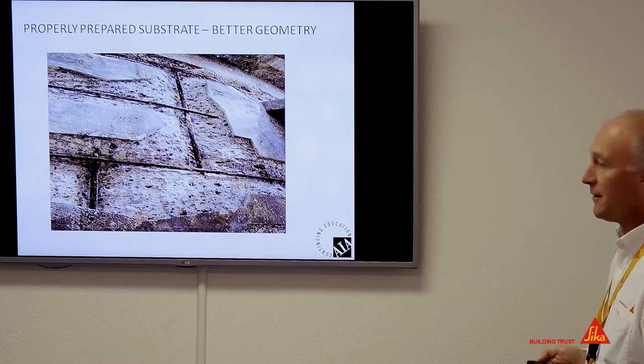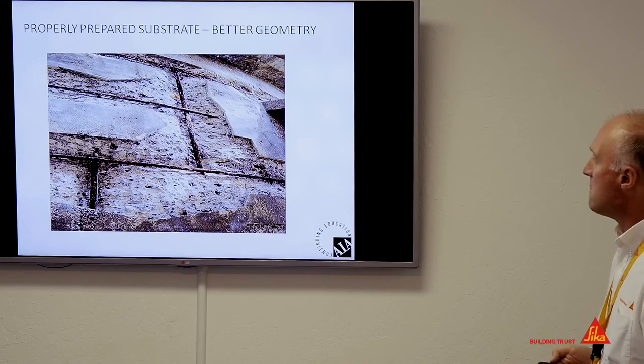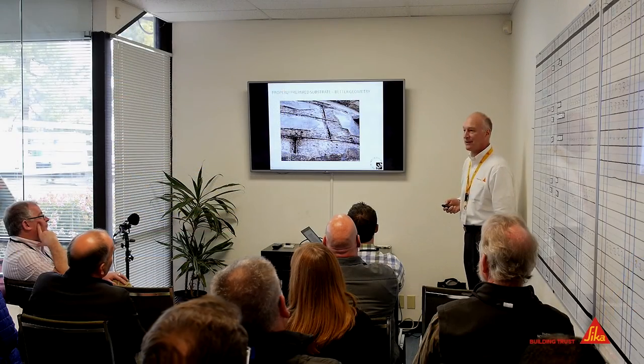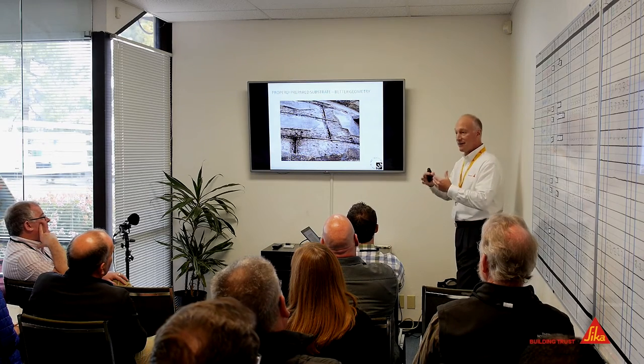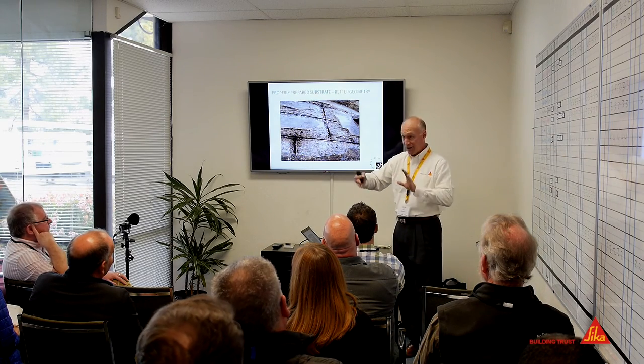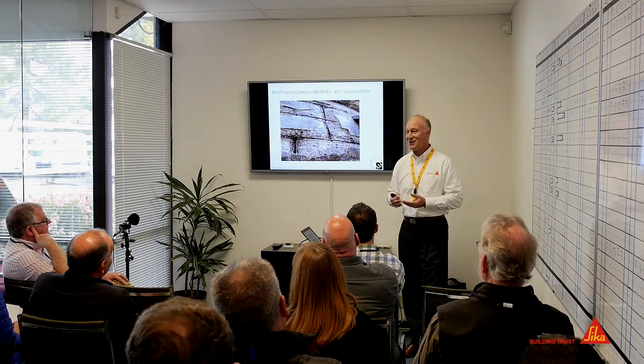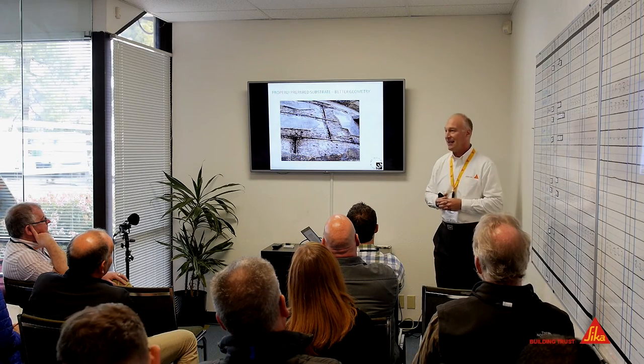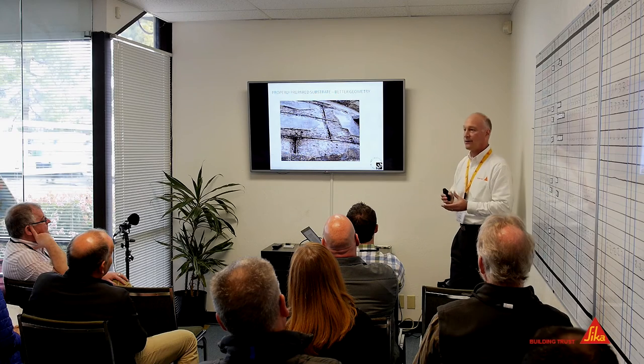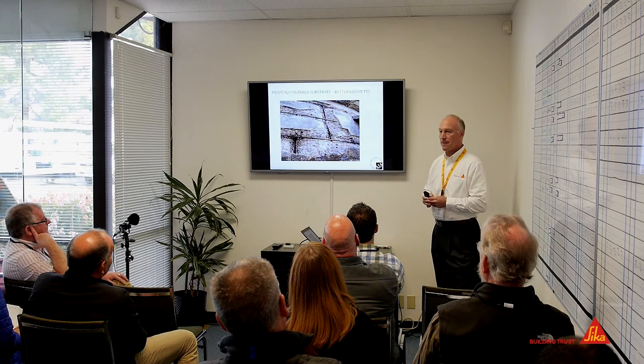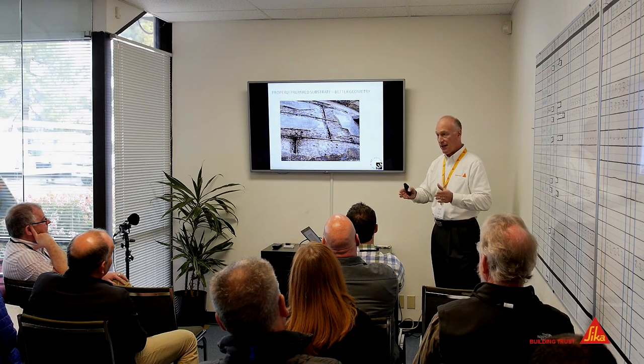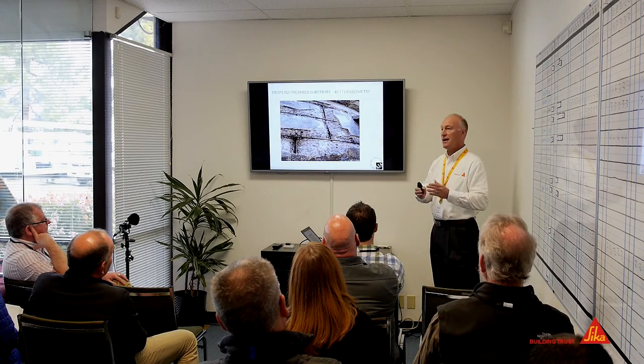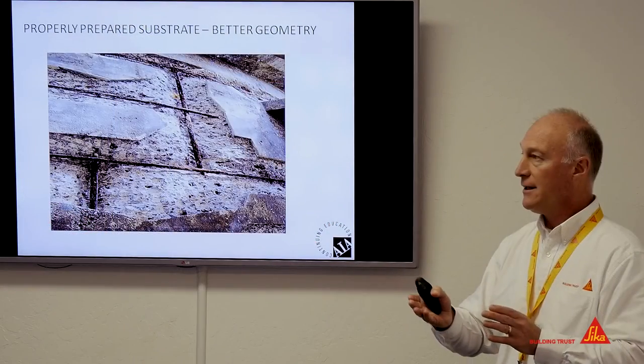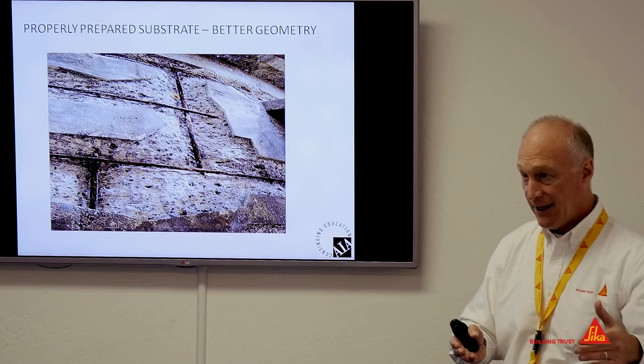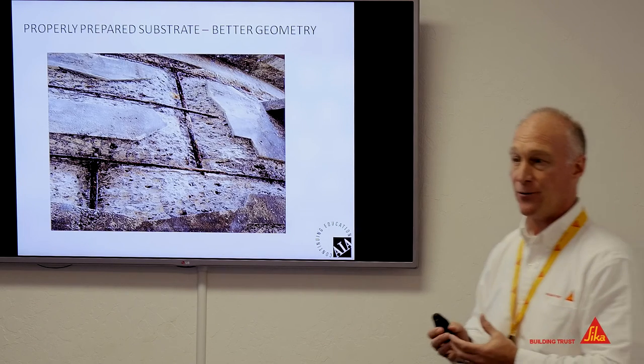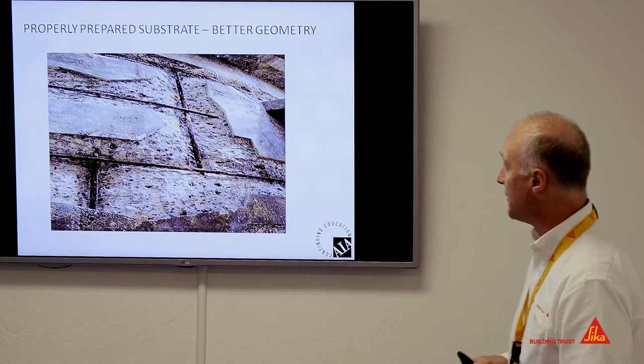Next step being... And you wouldn't go to a uniform depth everywhere? Seems thin. No, I don't believe you have to. If you go back to the guideline, they'll show a nice uniform depth. That was actually one of the discussions we had on a job yesterday. Again, it's really that level of reasonableness. As long as you get the delaminated concrete out, and you don't go too crazy, because you could induce some stress into the repair material. But in general, I think this is a pretty good job.